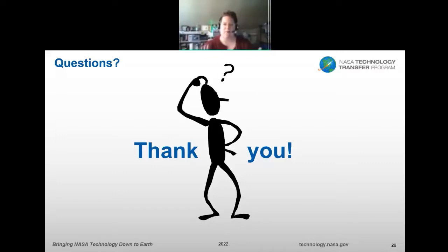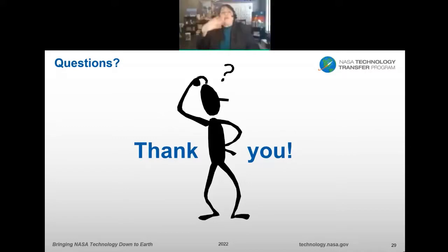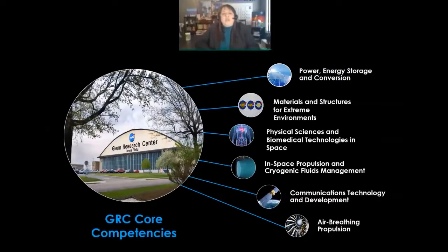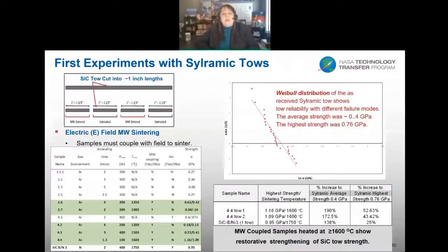Yeah, basically, why was the strength of the Tyranno and the Sylramic improved more so than the Hi-Nicalon through the microwave treatment? Oh yeah, the Hi-Nicalon already had a high strength. Okay. The Tyranno fiber had an average strength that we measured of about 0.4 gigapascals, and the Sylramic also had an average strength of about 0.4 gigapascals. So if you look at the slides, where we show the Weibull distribution, those are just showing us that there are failure modes in that particular tow, and that the reliability of that particular tow would be very low.